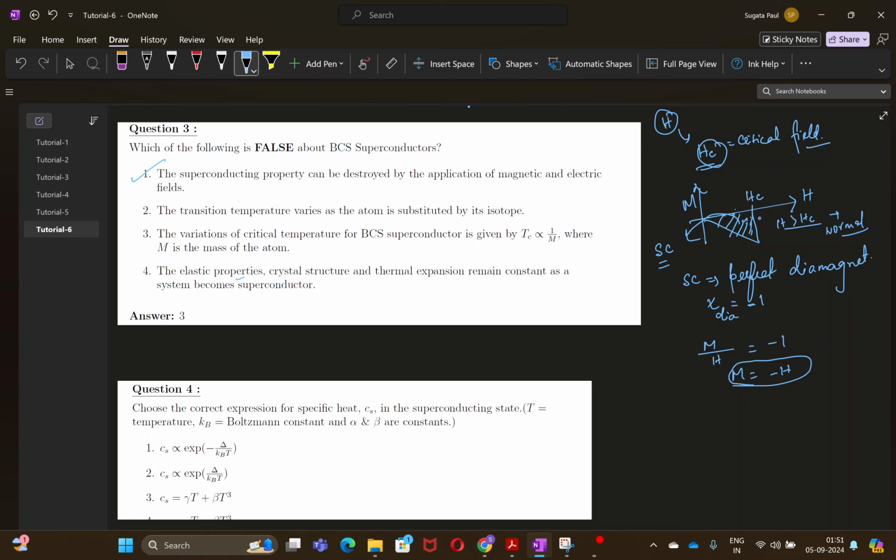That is because the Cooper pair, the main source of superconductivity, actually gets destroyed if you increase your field value beyond a certain critical point. You can think of it like this: Cooper pairs are formed of two electrons of equal and opposite spins, right? So if you apply a strong magnetic field which is beyond the critical value of the material, then that field will try to align both the spins along its direction.